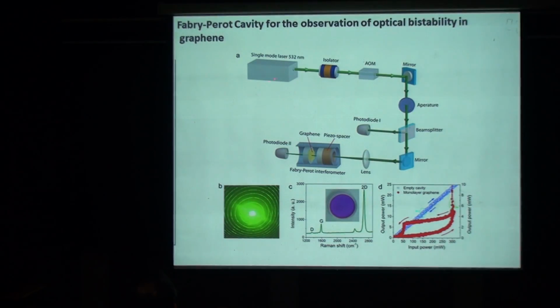So what we do is that we set up this Fabry-Perot cavity. We build it ourselves. In the Fabry-Perot cavity interferometer, you have 2 mirrors, and then you have light going in, focused through a lens. It undergoes internal reflection. When there's constructive interference, because it satisfies the dimension between the mirrors, the wavelength, or refractive index, you get these constructive fringes that you can see. Now, once you put graphene inside, you find that it can change the optical path by lambda over 2. Now, this is a 532 nanometer single mode laser. Lambda over 2 corresponds to 266 nanometer.